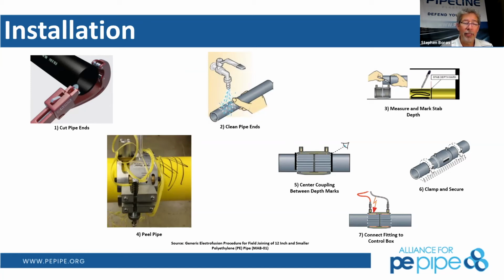You just want to make sure you're not introducing any kind of oils or anything like that into the process. Once you get your coupling centered on there, you apply the heating electrodes to it. The control box, then you push the button on the control box. It reads the type of coupler you have if you're using a universal control box, and it will apply the direct amount of current into those wires to get the right heat for the right amount of time. It monitors that, turns it off, you let it cool, and you're good to go.